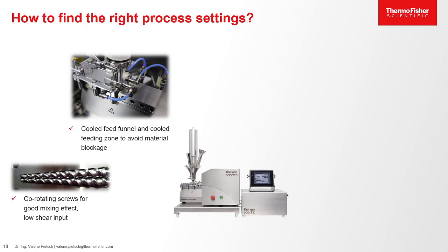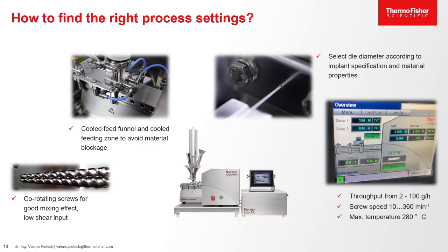Then the next part of the setup, which is quite important, is that we have a cool feed funnel that allows us to cool the feeding zone and to avoid material blockage in this section, which can of course also interfere with the complete process. And in the next stage, we have to select, of course, the diameter of our die plate according to the implant specification, but also material properties. So sometimes we have material that is a bit elastic and can be stretched, and this can be accounted for by selecting the correct diameter of the die plate.